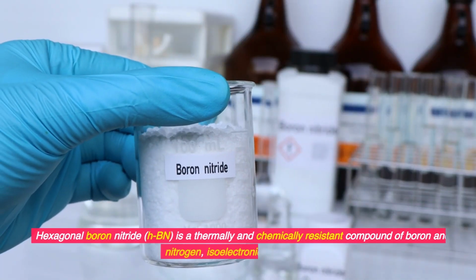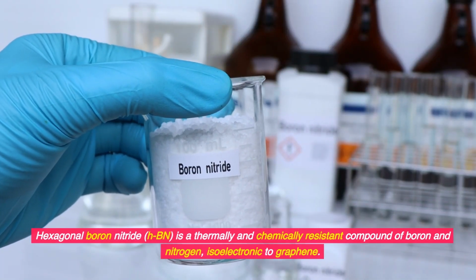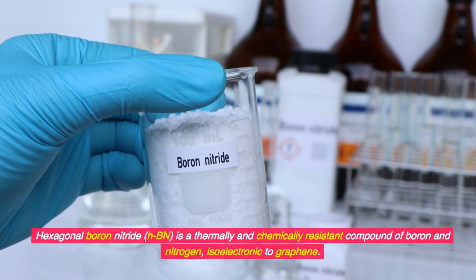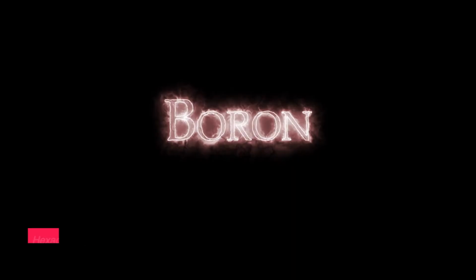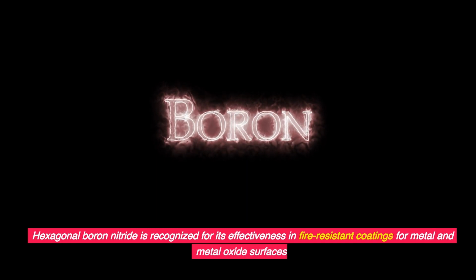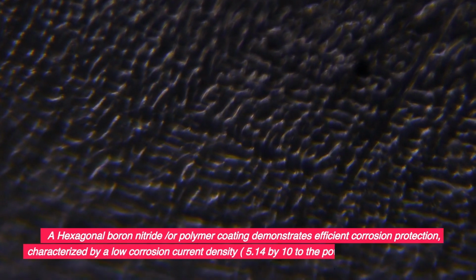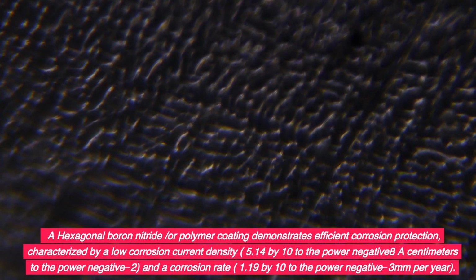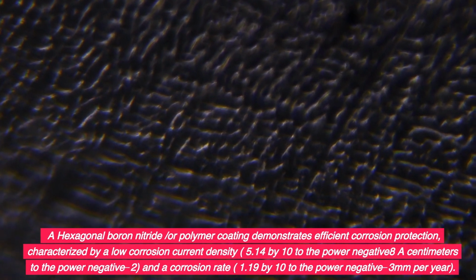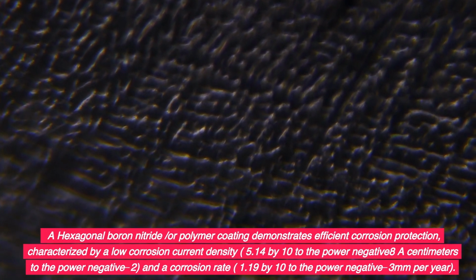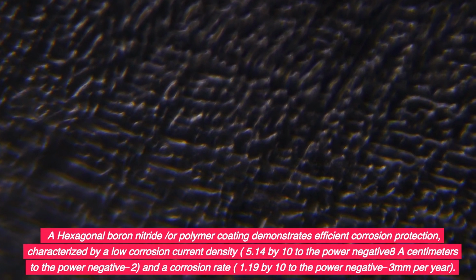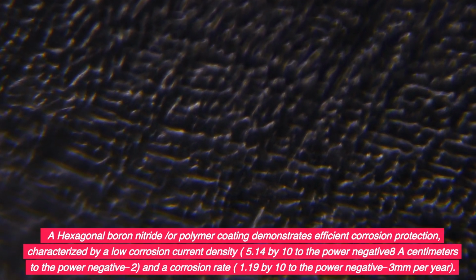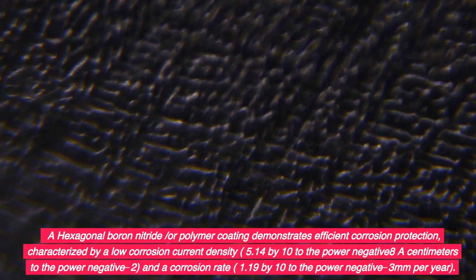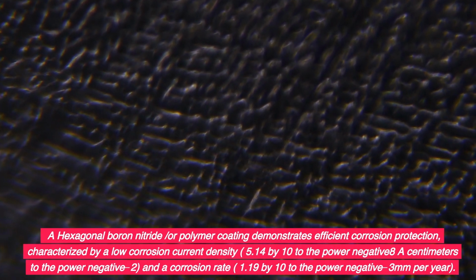Hexagonal Boron Nitride, HBN, is a thermally and chemically resistant compound of boron and nitrogen, isoelectronic to graphene. Hexagonal boron nitride is recognized for its effectiveness in fire-resistant coatings for metal and metal oxide surfaces. A hexagonal boron nitride or polymer coating demonstrates efficient corrosion protection, characterized by a low corrosion current density, 5.14 × 10^-8 A cm^-2, and a corrosion rate, 1.19 × 10^-3 mm per year.